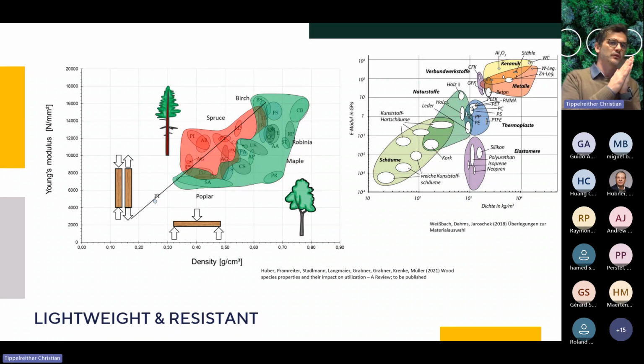And when we now use this benefit of the zero fiber angle and quite a good performance from the stiffness point of view and also strength, and look at it on the detail level regarding which wooden species are best in fit, you see that birch or beech are quite good wood species with this veneer technology. When we use thin veneer layers, we get quite good stiffnesses and tensile strength with a low density compared to other materials. And that's the reason why in the main of our product developments we get 10, 20, or sometimes up to 30% less weight, so we can produce lightweight components compared to glass fiber reinforced composite, or even to aluminium or magnesium and so on.